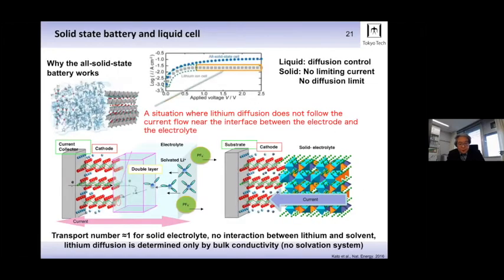I'll show you here one example of the advantage of all-solid-state systems over the current lithium-ion system. Simple electrochemical measurements on both the solid and liquid systems show a limiting current for the liquid system, but not for the solid system. This means that the high current capability of the solid-state battery is due to either the higher diffusion of lithium ion in the electrolyte than in the liquid, or the larger concentration of lithium ion in the solid electrolyte than in the liquid electrolyte. In other words, the high current capability of the solid-state battery is an intrinsic advantage of using the solid-state form for batteries. The ion transport number of 1 for solid electrolyte is a major reason for this advantage.